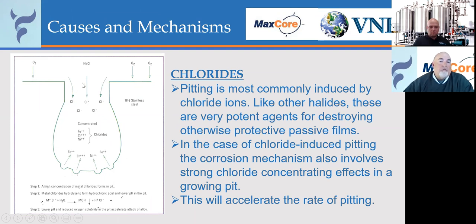And as this starts to fill with the solution, it becomes more corrosive because of the concentration that's there, and you no longer have any type of flow within that type of pit. And as this starts to grow, not only have you got a more aggressive solution, but you also have a much larger anode as that starts to grow. So your anodic site gets bigger and bigger, and therefore you have a much faster rate of exchange that can take place at that. So whenever you have pitting taking place at that location, a lot of times it can drill through stainless steel very, very quickly and can cause a catastrophic failure much quicker than you think it can.